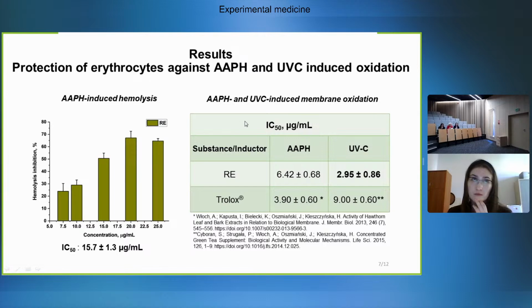The protective impact of the extract was checked on both erythrocytes and erythrocyte membranes. And here we have the graph that illustrates the hemolysis inhibition of the extract as a function of concentration. The oxidative stress was induced by AAPH, and we saw that the hemolysis was effectively inhibited by this extract, and the IC50 was only around 15.7 micrograms per milliliter. And here on the right, we have the results from the erythrocyte ghosts, which are the membranes, and we showed that the extract is effective against oxidative stress from both AAPH and UVC, and against UVC, the extract has a much better effect than the standard antioxidant.